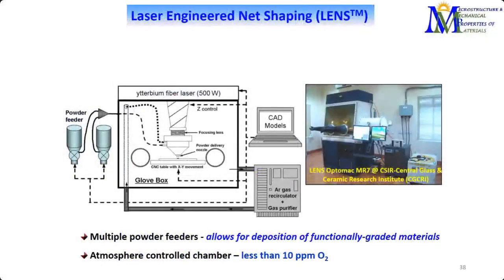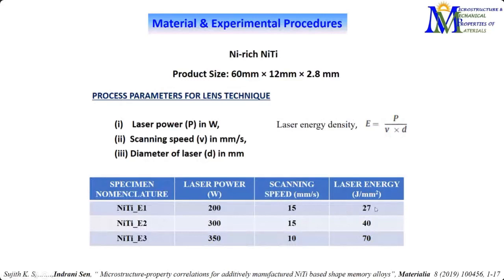Now, when we talk about medical applications, we often need very complicated and miniaturized shapes, hardly a millimeter in size, and it is even used as sensors in MEMS. So we have micron-sized devices and implants that need to be made, and often we have to take advantage of additive manufacturing. For this particular work, we used a LENS system to produce the nickel titanium component, and in the process we varied the processing parameters. We used three different laser energy densities, from 27 to 70 joules per millimeter squared, varying laser power, scanning speed, diameter, etc., resulting in three different laser energy densities, although we started with the same pre-alloyed nickel titanium powder.